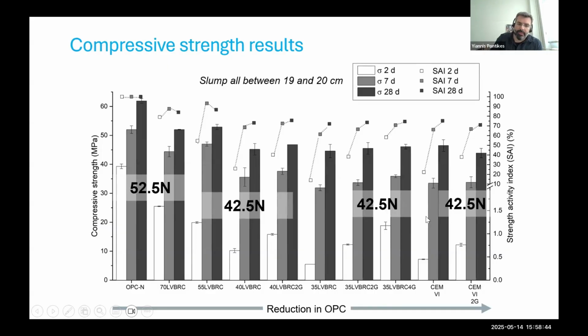And it's good. It's good because at 70% LVBRC, you're on the 52.5 N. You're a bit short on the 2 days, but then you're catching up. And then in the other formulations, you're always on the 42.5 category. And that is very, very exciting because it means you create now this substitute for cement clinker, but you're not compromising on performance. And if you see our latest data and our new formulations, they're even better. But okay, I cannot speak much about them. So there is hope that this can also decarbonize the cement industry and save some CO2 from being emitted.